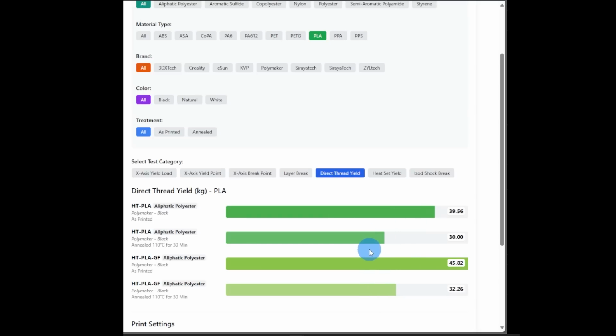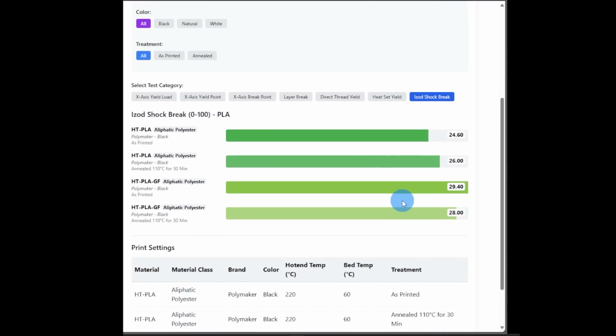Direct thread, High Temp PLA glass fiber, unannealed, held on best, and on both of them, once they were annealed, the strength went down. Heat sets, strength dropped off considerably on the annealed parts. I don't have an explanation for that. And finally, the IZOD shock.